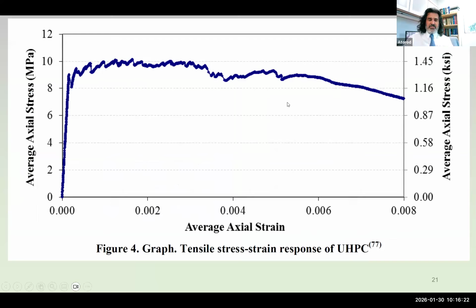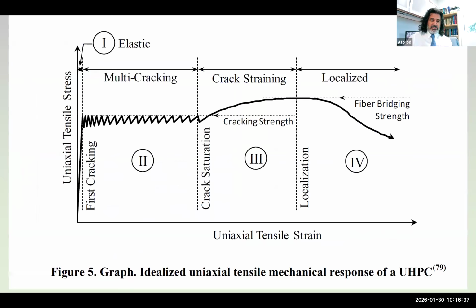The other aspect is that UHPC, once it cracks, because there are lots of steel fibers in there, those steel fibers hold on to the crack and don't let the cracks open until one crack takes over. So here is a stress strain curve. You can see that once you load it, there are multiple cracks, and then there is one crack that takes over.